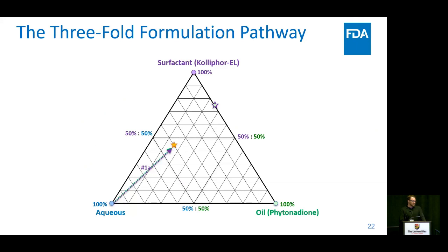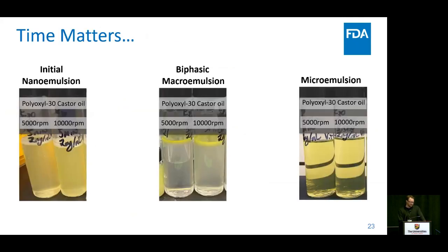And so what ends up happening there, you get this kind of coarse nanoemulsion, depending on the homogenization speed you are using. And then after 24 hours, oh no, it splits. So it looks like it's doing that classic phase separation behavior. But if you just leave it at ambient conditions for about a month, what ends up happening is it produces this full microemulsion again.